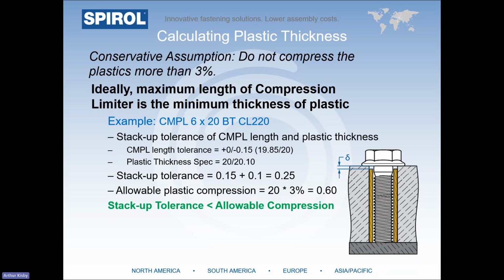If we compare the tolerance stack-up to the allowable compression, or 3% of the 20 millimeter length, it's about 0.6 millimeters. So we can see that the stack-up tolerance isn't going to be a problem, as it's less than the amount the plastic will be able to compress safely.